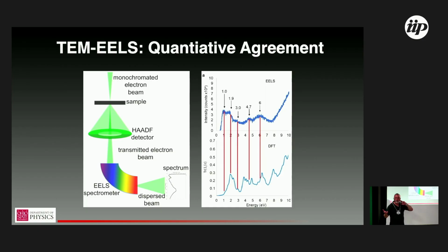That's the spirit of what I was saying with completely butchered language, which I apologize for. Theoretical obsession. The bottom line is we start from the DFT calculation of the density of states, then apply the appropriate physics to imagine how that compares to the experimental observable, which is effectively the dielectric function, and find extraordinarily good agreement, including with the band gap. There are a lot of phenomenological aspects of the experimental measurement, so I wouldn't take the amplitudes of these different curves too much to heart. It's more the energy alignment of where the various states exist. And we find quantitative agreement that's shockingly good, I would say, for this kind of comparison.